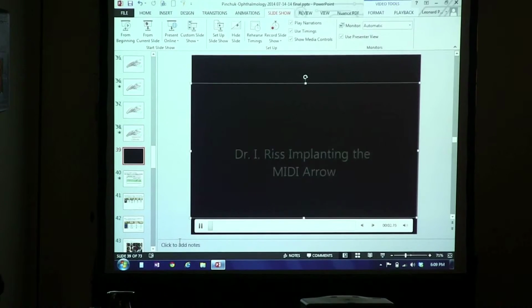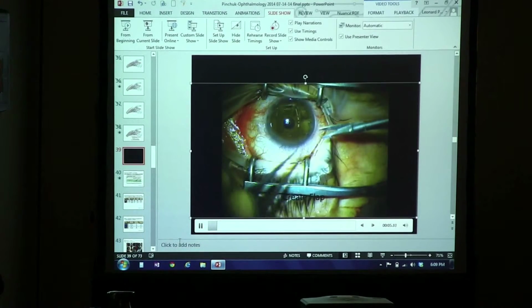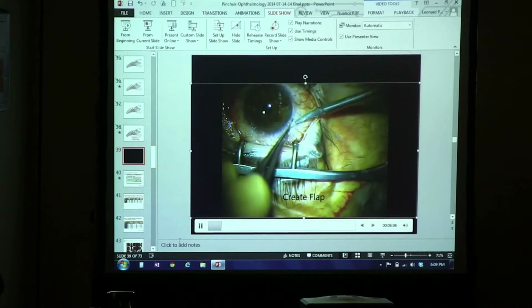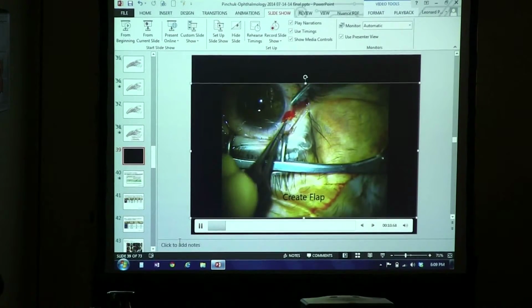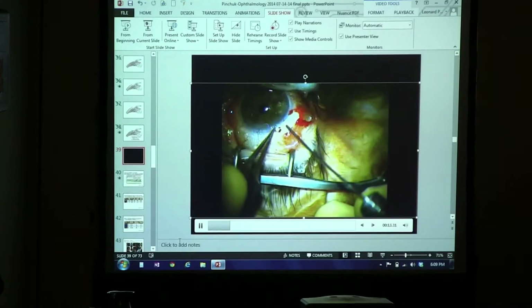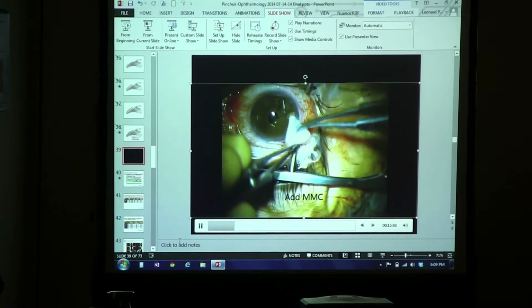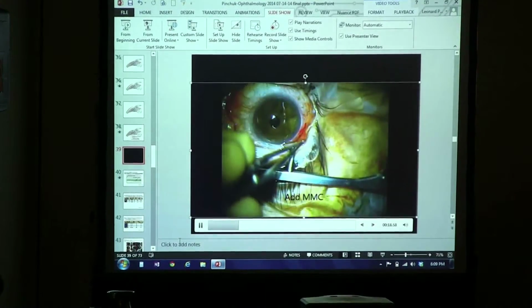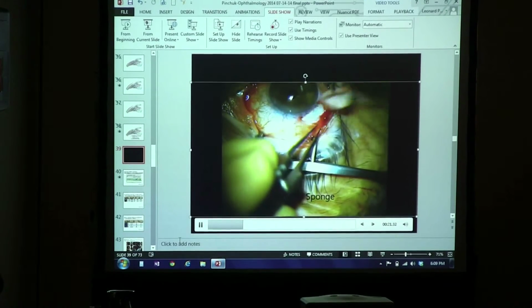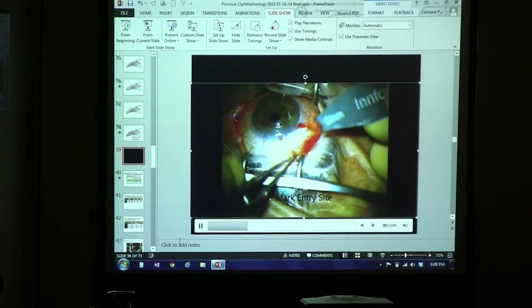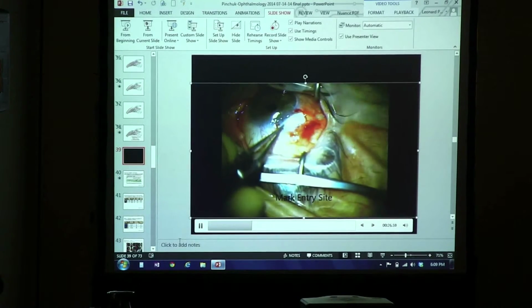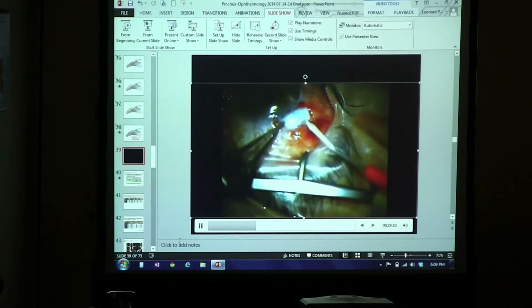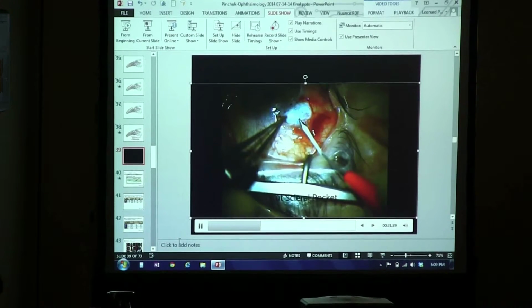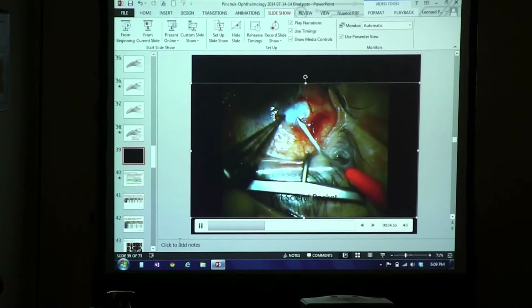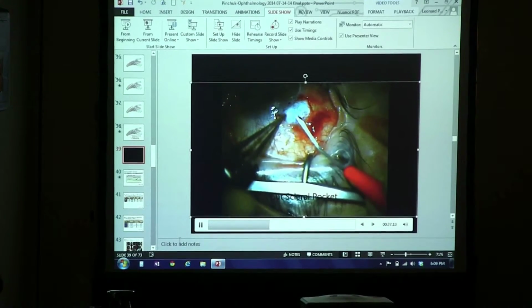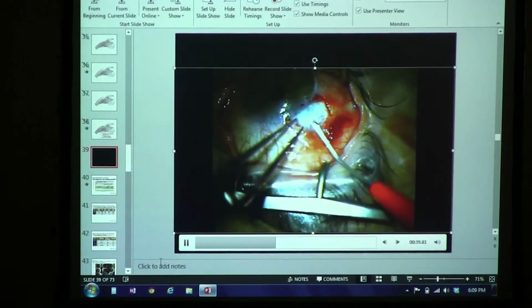All right, so this is Isabelle Riss in Bordeaux, France. So what you do is you form an incision in the limbus. This is a fornix-based flap. Dissection under the flap. And we use Mitomycin C in the United States. Over here, you have to put it in with pads because it's not FDA approved otherwise. You make a mark about 3 millimeters below the limbus. And we use a little knife to make just a little pocket over here. And these are going to hold the fins. So it's about 1 millimeter wide, about 1 millimeter deep.